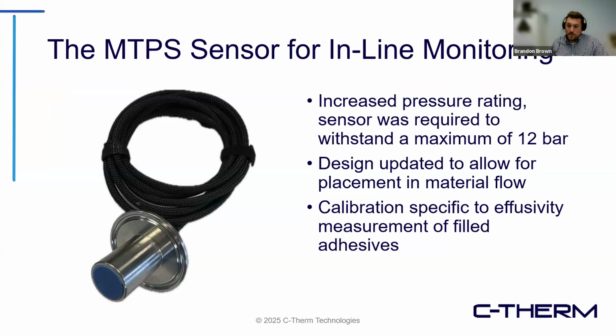So here we see the sensor with some modifications for this specific implementation. At this new location, the first concern was that it was required to withstand a one-sided pressure of 12 bar, or about 175 psi for us North Americans. It took some thinking to get past a few of the devilish details, but we ended up finding a solution. The sensor was also modified so it could easily be inserted and removed from the adapter blocks, and a gasket was used to make sure there's no leakage.